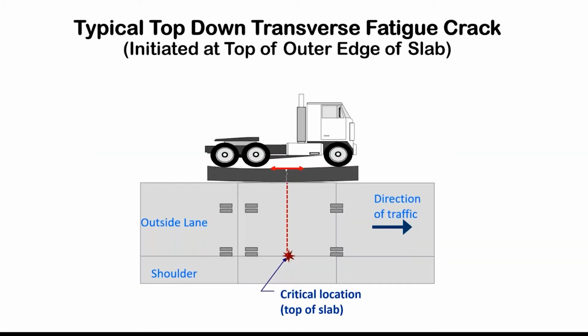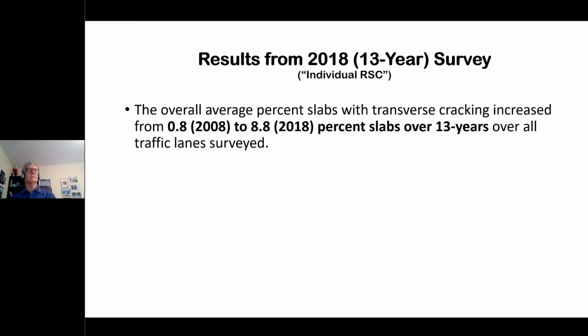Just to give you a little better view of the cause of that, you see that truck loading the slab, where most slabs are curled up. Well, that produces a high stress in the top of the slab. Well, multiply that times millions and millions of heavy repetitions. It works its micro crack starts across the slab, down through the slab, and creates eventually a crack that can break down. It can lead to other kinds of cracking. So it's the kind of thing you want to minimize in design, so you get long life pavement.